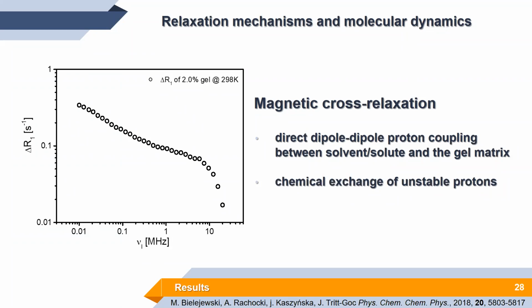The first one: either we have direct dipole-dipole interactions between the protons of the diffusing molecule and the protons coming from the internal structure of the gel matrix. But we know that in the case of the ionogels, the ions are surrounded by a solvation shell created from the solvent molecules, and also the surface of the gel matrix is covered by water or other liquid molecules. So there is a very low probability that the ions will directly interact with the surface of the gelator aggregates.